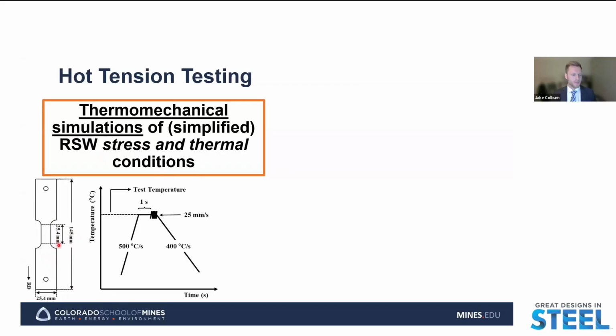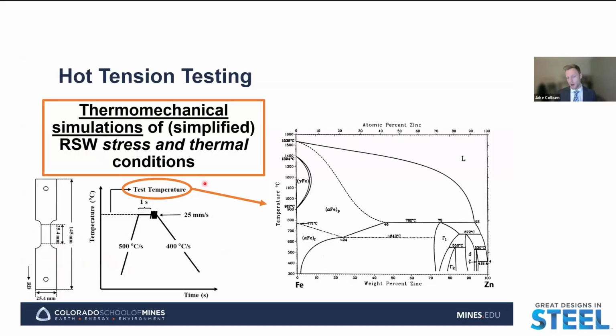Here we have our tensile specimen that will be rapidly heated up to our test temperature, held for a short amount of time, deformed to failure, and then rapidly quenched. The test temperature at which we choose to hold the material is important for both the underlying substrate microstructure, but also in terms of what iron-zinc intermetallics we could potentially expect to be present upon deformation.